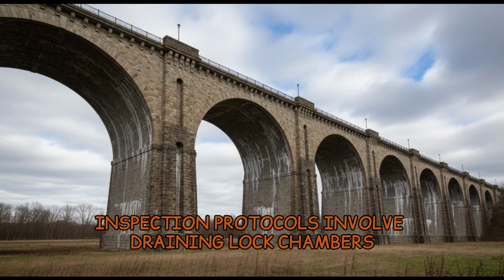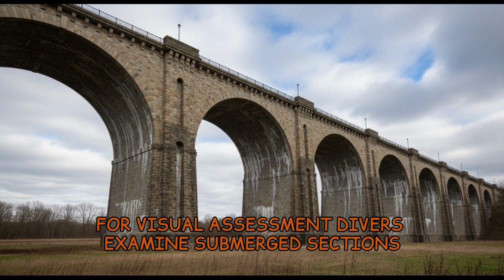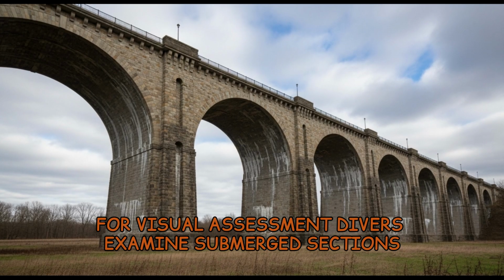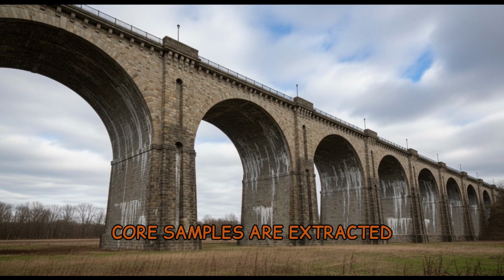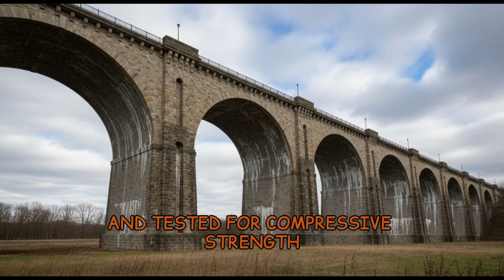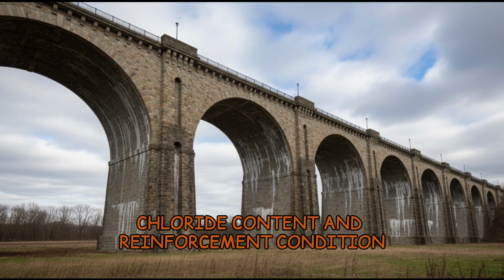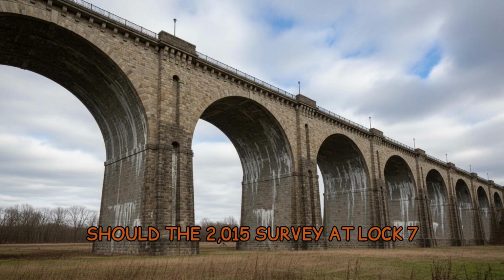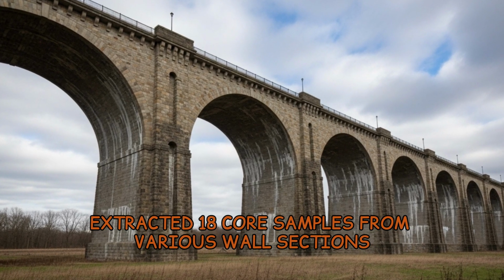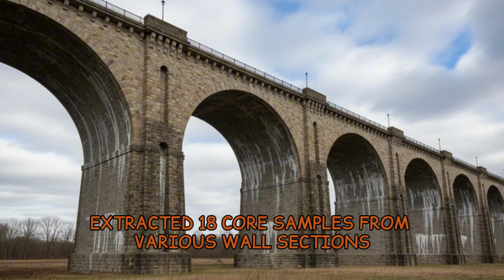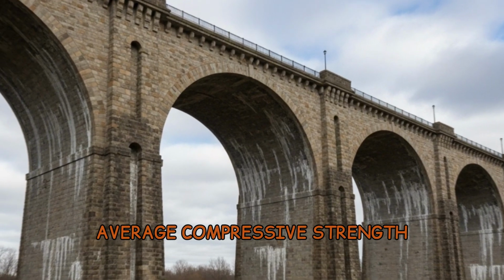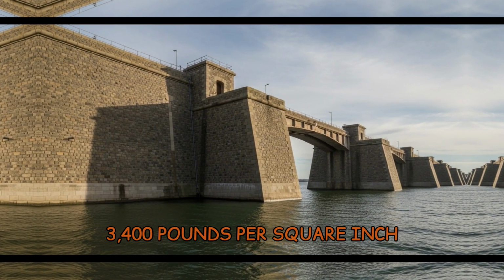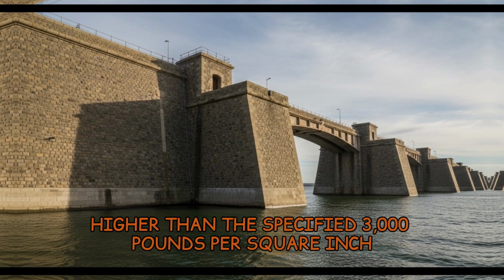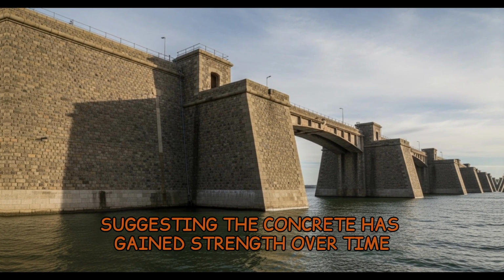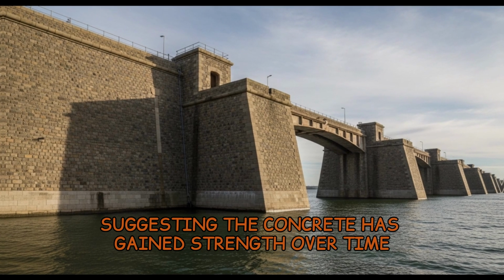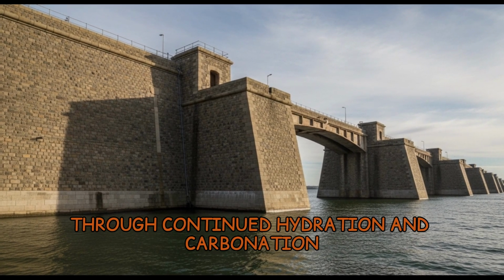Inspection protocols involve draining lock chambers for visual assessment. Divers examine submerged sections. Core samples are extracted and tested for compressive strength, chloride content, and reinforcement condition. The 2015 survey at Lock 7 extracted 18 core samples from various wall sections. Average compressive strength, 3,400 pounds per square inch, actually higher than the specified 3,000 pounds per square inch, suggesting the concrete has gained strength over time through continued hydration and carbonation.